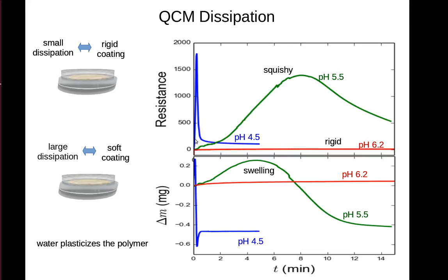At a pH of 4.5, the resistance goes up very quickly as the polymer swells, but then immediately drops within under a minute, approximately 30 seconds, as the film dissolves and the energy dissipation decreases rapidly. At a pH of 6.2, the polymer film stays fairly rigid and never requires much energy. At a pH of 5.5, the swelling causes it to become very squishy or jello-like, dissipating quite a bit of energy, and then as it dissolves, the amount of energy required decreases.